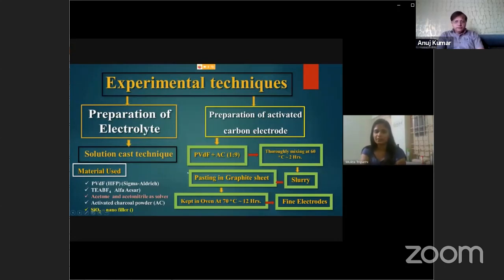Okay, so for the activated carbon, we have chosen PVDF HFP, and the activated carbon, maintaining a ratio of 1:9. After that we mix it thoroughly for 2 hours at 60 degrees Celsius. Then we get the slurry, and that slurry has been kept at 70 degrees Celsius for 12 hours. Then we'll get the fine film of the electrode. So this is the preparation of the electrode material.